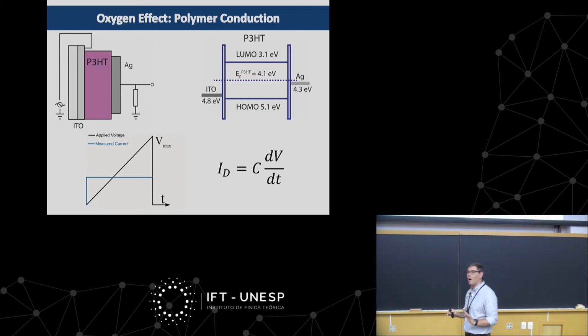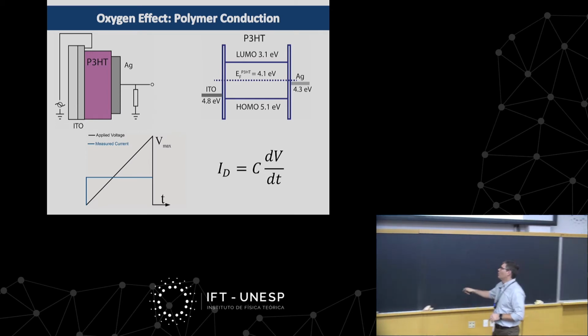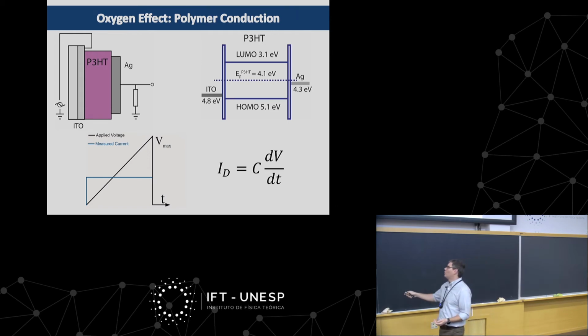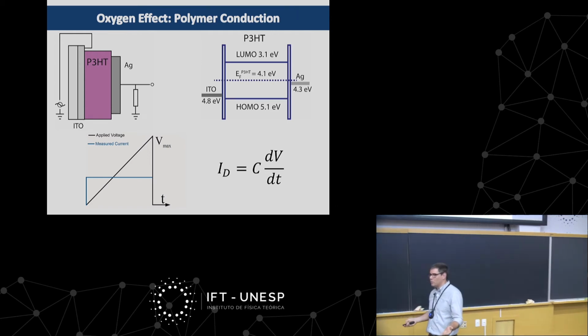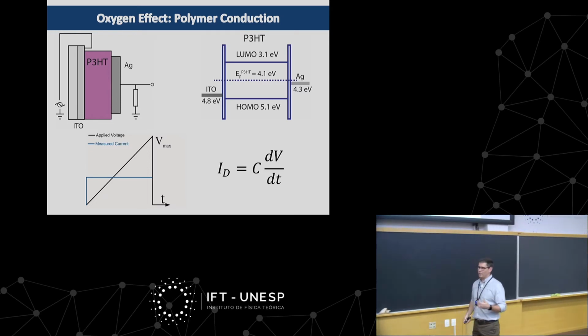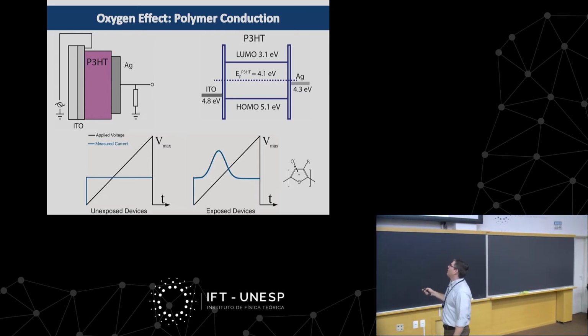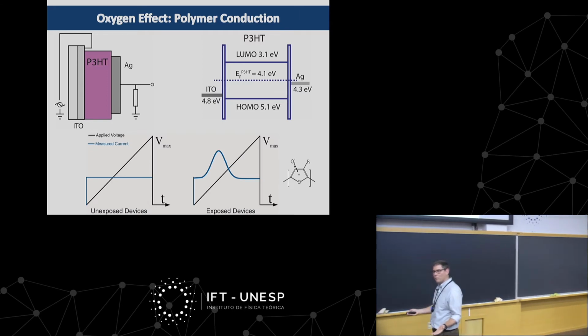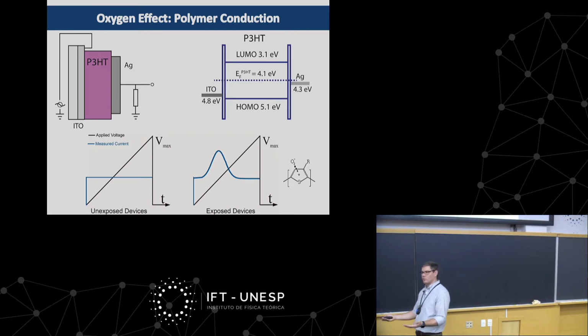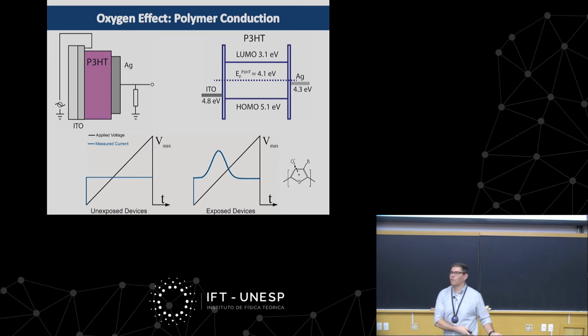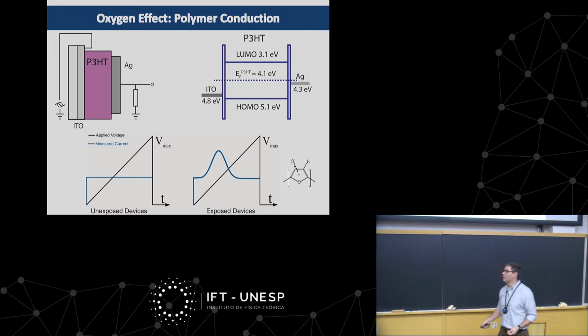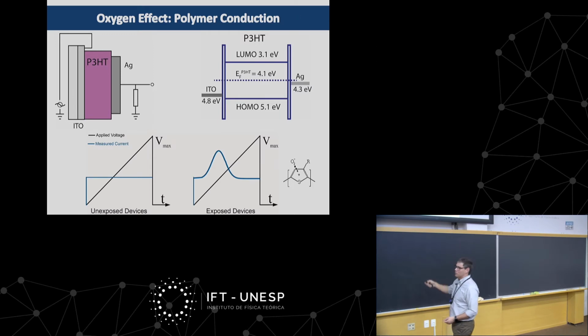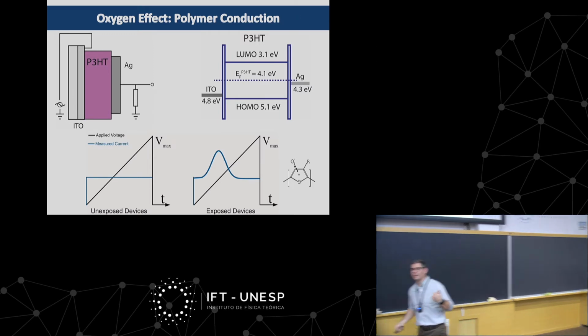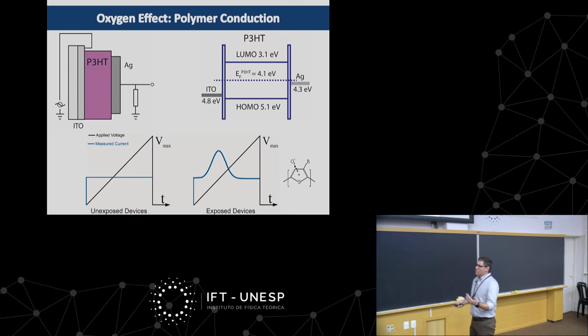So the idea is, okay, if the polymer is neutral, so it's not exposed to oxygen, doesn't see oxygen at all, so the polymer is completely neutral, there is no charge in the polymer. So when I apply this linearly increasing voltage, I would see simply this step current, which would be associated with the capacitive response. Then when I expose my device to oxygen, I would create those charge transfer defects, and therefore I would p-dope my polymer, and then I would be able to extract those holes that are left behind on my polymer.